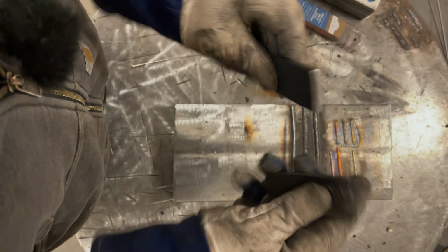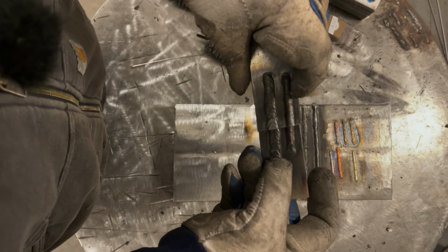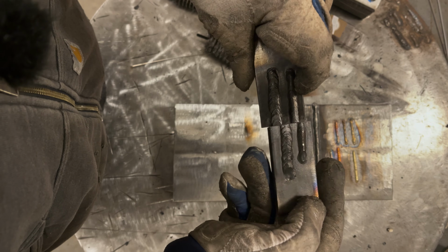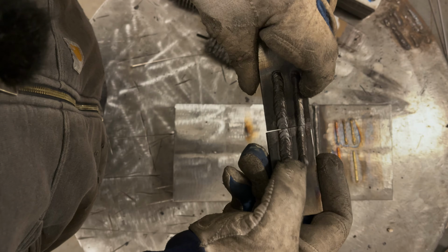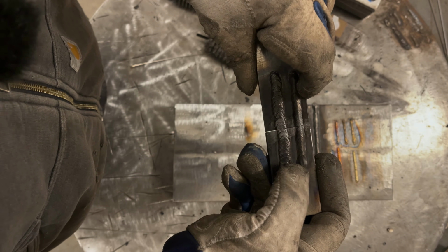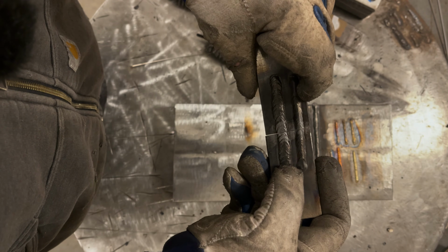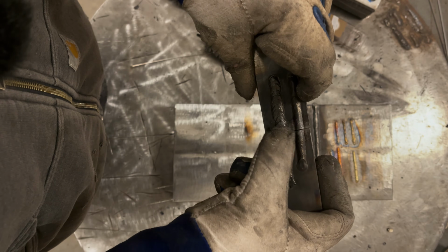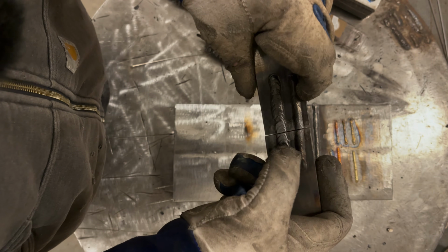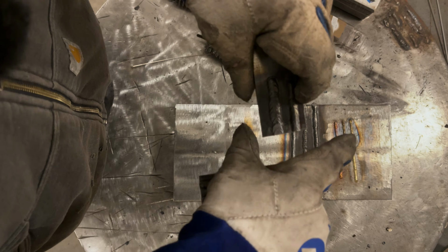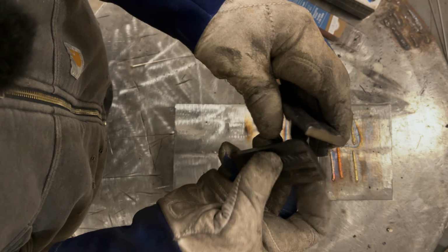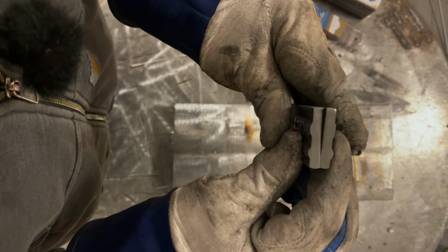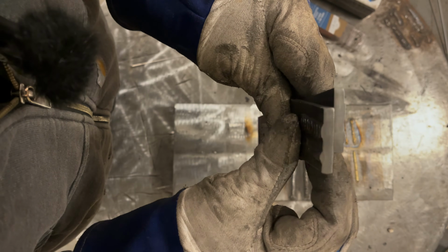All right, guys, let's see what we got here. I cut the plates, etched them. We have the 60-10 on the bottom, 70-18 on the top. Now the 60-10 is wider, and that's simply because my travel speed is lower. The 60-10 likes to have a wider weld, and that's simply because the arc cone that comes off is wider than the more direct 70-18.